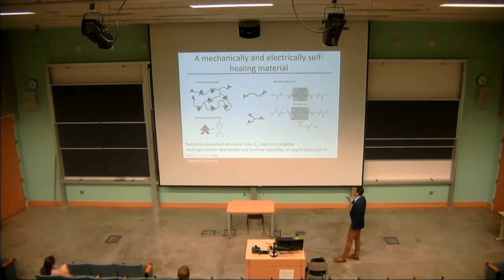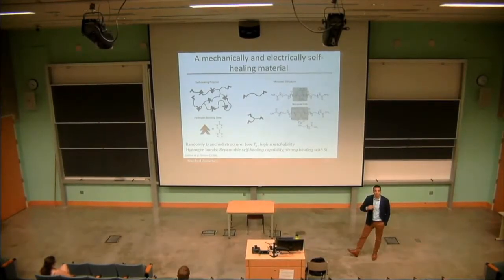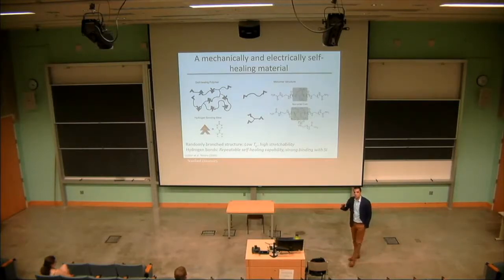Additionally, because these are hydrogen bonds, they're completely dynamic, and the self-healing capability is completely repeatable. So it can happen as many times as you need it to, and this network is actually dynamically rearranging all the time. And then, as I mentioned before, these hydrogen bonding groups have strong association with the silicon surface. And so you have strong interactions with the particles that, again, help to maintain the connectivity of these electrodes.